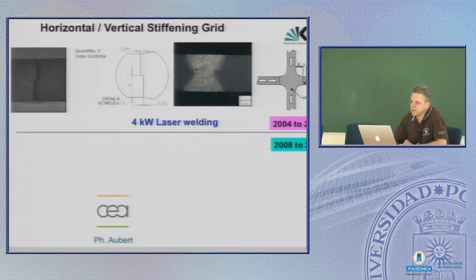Okay, the problem here is not welding. This can be done preferably by laser, but also TIG welding. The problem here is that you have to perform these weld lines in a box, which is almost a meter deep, and, well, by hand it's not possible. You cannot crawl through these boxes or whatever. So the problem is to have a tiny aperture to go where you can go back and forth and weld this.